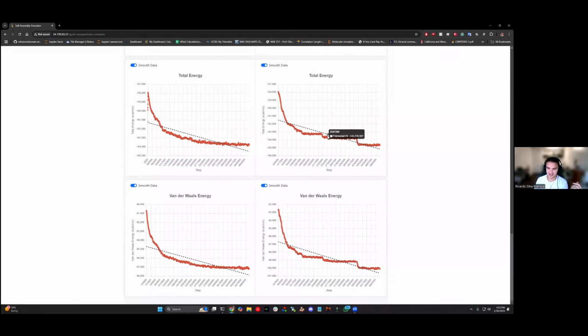But the difference is that here in this system, you see some drastic peaks over here that drop in energy, which means that, okay, the system was already kind of stable with these nanoparticles, but eventually two bigger nanoparticles clumped together, and then the overall energy of the system lowered a lot. And then even bigger two nanoparticles clumped together again, and then the system dropped even further in energy. While here, basically, it's just a reorganization of the unit cell, and you don't see these bigger nanoparticle clumpings because the citric acid is already kind of blocking that from happening, right?